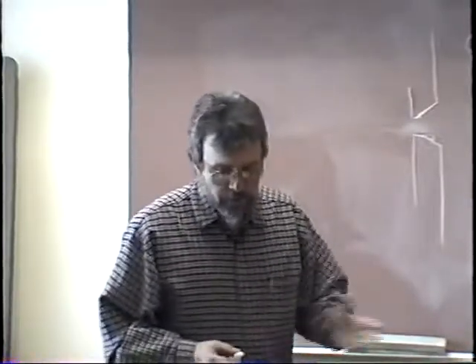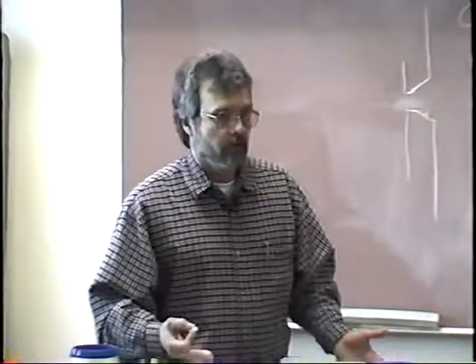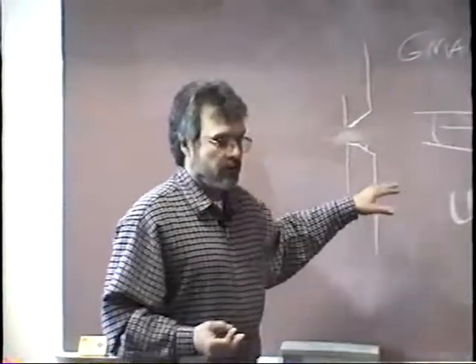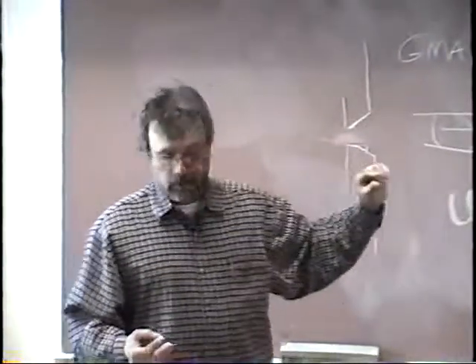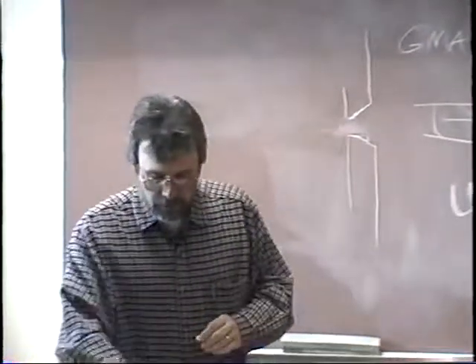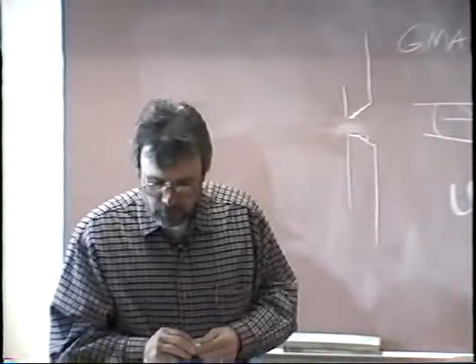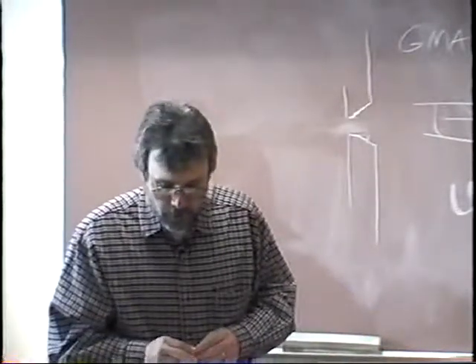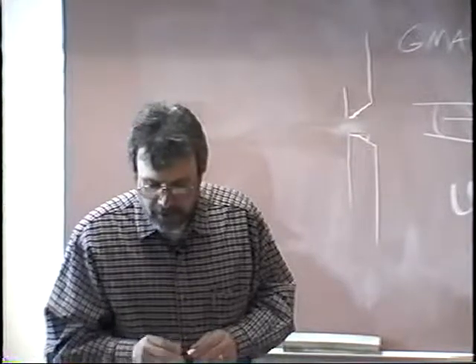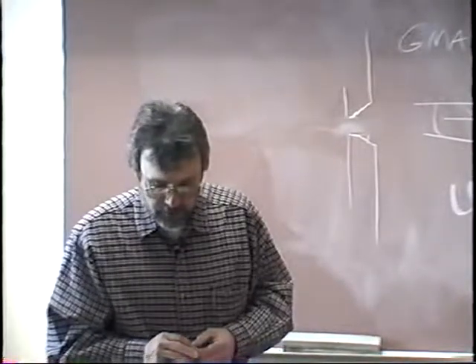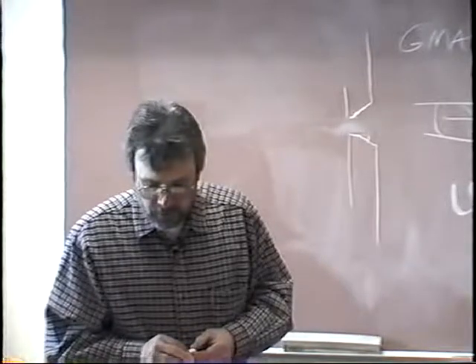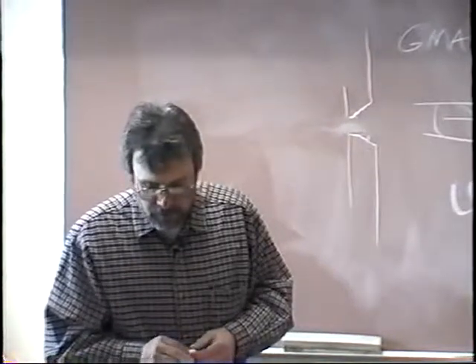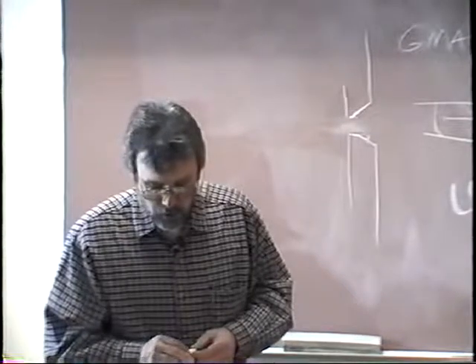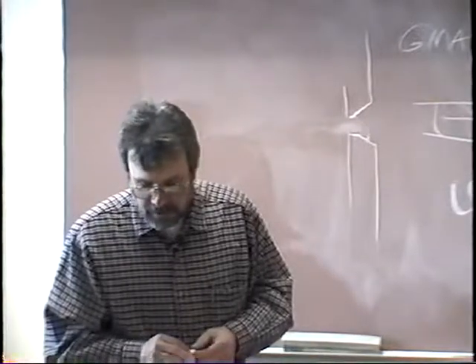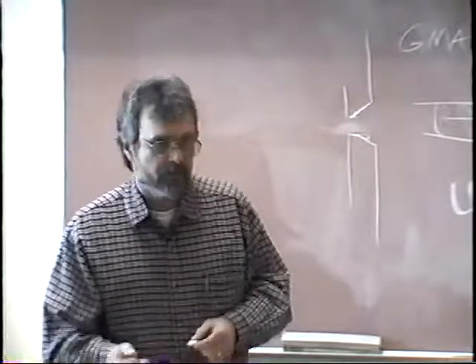Over on page 143, continuing with bad fit-ups, what happens if it's too narrow? Say this is too tight, and this is a common thing. If the root opening is too narrow, what are you going to do? Well, your text says that when the root opening is too narrow or is closed entirely, the root bead can be welded by using a higher current setting and a normal arc length. This will increase the heat input into the weld and the penetration. The puddle must not be allowed to become too large or it will sag. To prevent sagging, it may be necessary to resort to the whipping procedure.